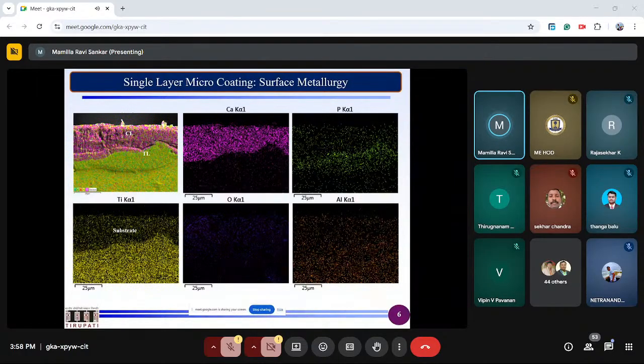Titanium is a highly reactive material, and at the same time it has low thermal conductivity. The good thing about it is that you will have a better transition layer, which means proper bonding and other things. Once you coat, you can also check elemental mapping and so on. Many mechanical engineers may not be well aware of elemental mapping. When you use the SEM or FESEM process, you have four options in EDS, energy dispersive spectroscopy: point analysis, line scan, area scan, and area elemental mapping.